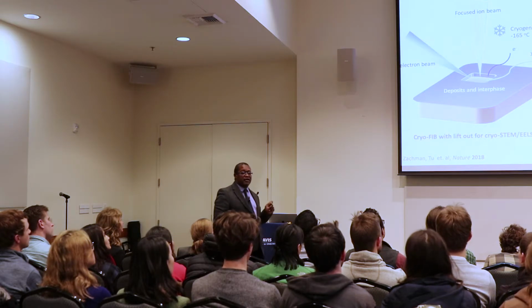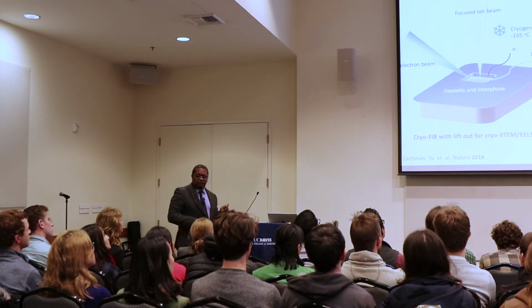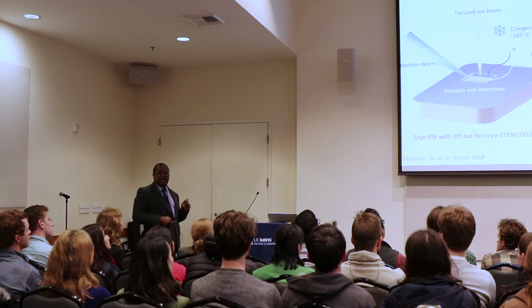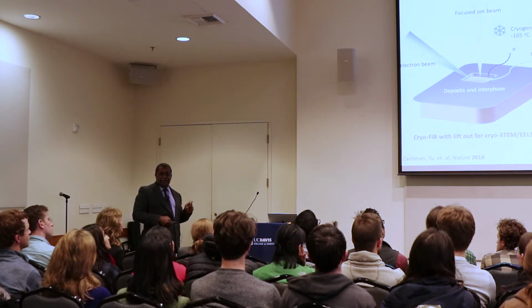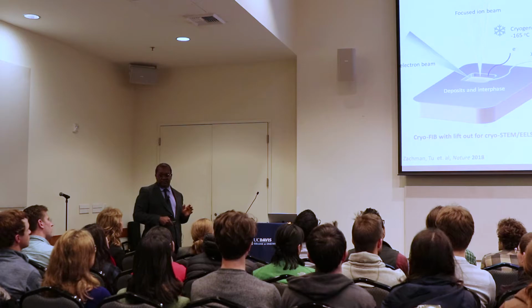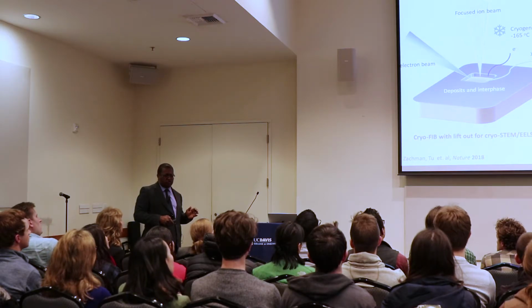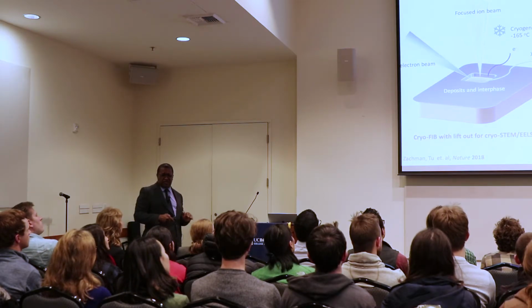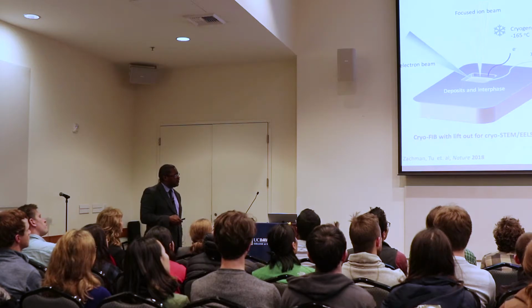Whereas people used to think that this SEI layer, this patchy layer, was just about 15 nanometers thick, we found it to be hundreds of nanometers thick. It's huge, and it's messy, and it's patchy, and it sequesters things in different locations.